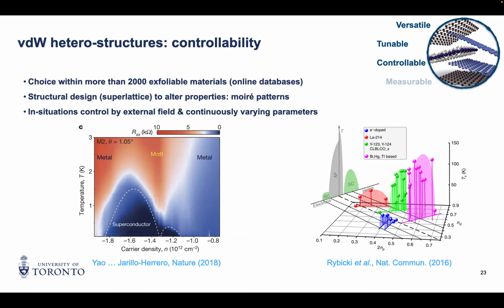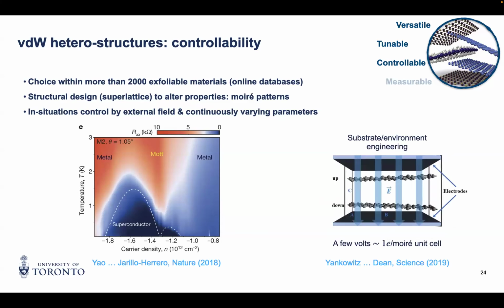You should compare that to the traditional way we got phase diagrams in condensed matter with 3D bulk, by changing some parameter as we grow a material, typically the doping or concentration of some atom, for many material families. Then we project that onto some hyperplane, and we hope that all the data is consistent and makes a consistent whole. That's, for instance, the phase diagram of the cuprates, and here you get something that looks pretty much alike, but still in one sample only. The reason for that controllability is that if your system is two-dimensional, you still have one direction of space to engineer something and control the system. In that case, the material was just put in a capacitor. By changing the gate voltage on the capacitor, you can change the chemical potential. And by changing the chemical potential, you change the carrier density or things like that. Right.